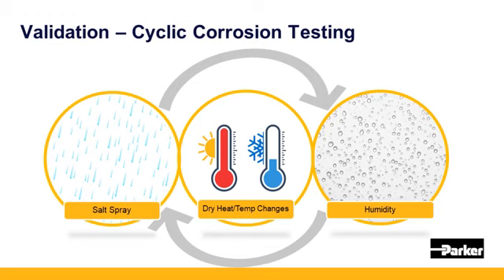Therefore, over the years, a series of cyclic corrosion tests were developed and evolved. Cyclic corrosion test combines segments such as salt spray, rain shower, and fluctuating temperature and humidity cycles. For example, dry heat, or lower temperature but higher humidity to create condensation. Those critical segments operate in a cycle throughout the test. Cyclic corrosion test duplicates naturally occurring corrosion events under a well-controlled environment. Therefore, cyclic corrosion tests can provide better correlation with the real-world exposure.